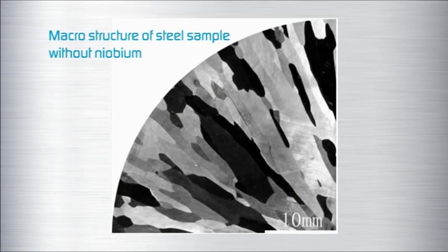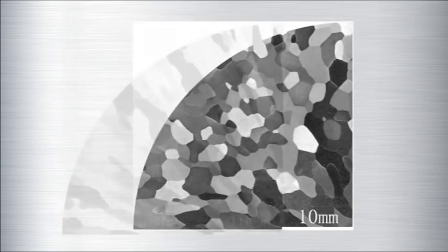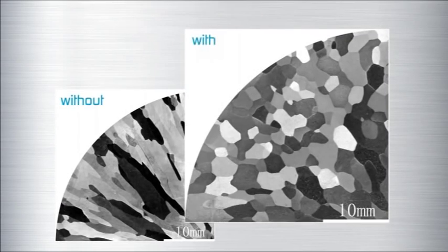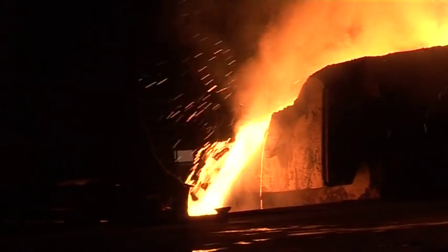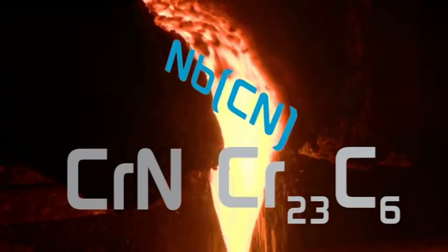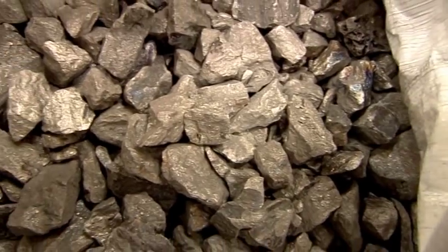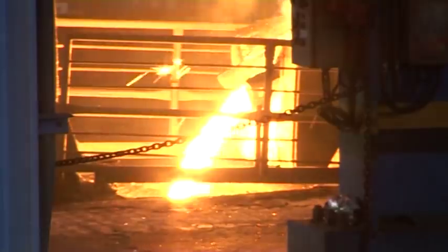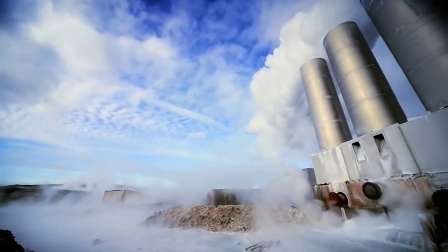One very important new observation reveals how niobium in particular enlarges the solidification interval during casting, which in turn leads to more effective grain refining with improved strength and formability. This development will further enable ferritic steels to penetrate the market currently dominated by the more expensive nickel-containing austenitics, for example in household appliances and construction. As in other stainless steels, niobium is also available to preferentially combine with carbon and nitrogen to suppress the formation of chromium nitrides or complex chromium carbides.